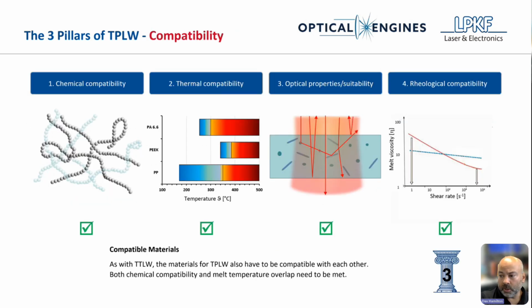And material compatibility obviously is important. You couldn't weld a silicone to a PC. It just isn't going to work because of the molecular combinations. So chemical compatibility, thermal compatibility, so roughly a 50 degrees C overlap in melt temperatures. Then basically the optical properties need to be suitable, like I discussed. Certain materials just aren't going to pass enough of that laser energy, okay? And then we obviously need rheological compatibility, melt viscosity, shear rate.